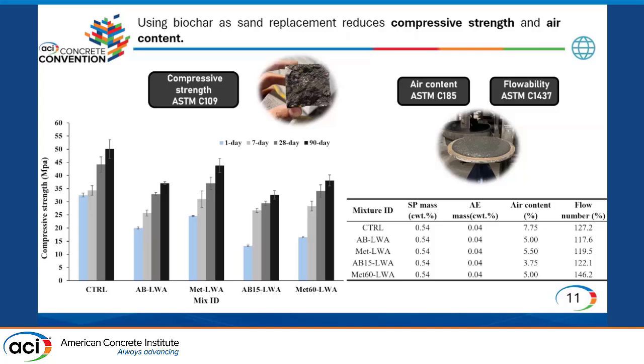And these biochars, keep in mind, were added in pre-soak state. So we pre-soak them in water 24 hours before the start of the mixing to make sure that their pores are filled with water so they don't absorb any water, because the water absorption capacity is exceptionally high. So we want to make sure they don't absorb any water that was meant to react with cement.